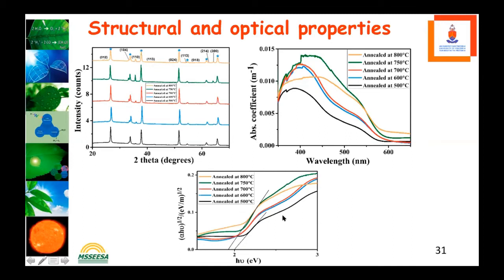After we have done this, we find that we're able to work on our band gap for this hematite. You can see that with the annealing at 500, it gives you exactly 2. But if you anneal at 750, you can lower the band gap.